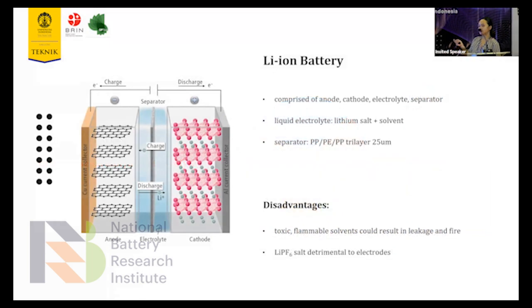This is the scheme of lithium-ion battery. As we can see, we have two sides of electrode, which is anode and cathode. And we also have electrolyte and separator. The electrolyte is made of the commercial one. We have liquid electrolyte, which is comprised of lithium salt dissolved in carbonate solvent. And the separator is made of Celgard separator, which is a 3-layer polypropylene, polyethylene, and polypropylene.